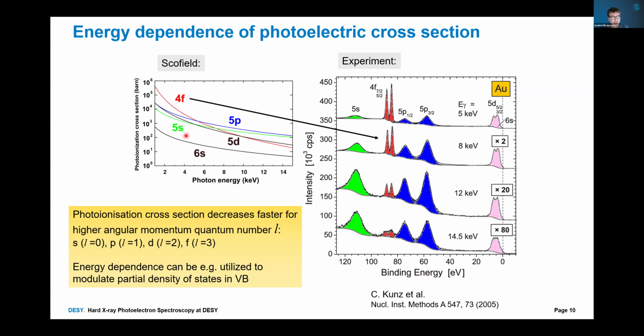and P lines. But this can be used to our benefit, because we can utilize it to modulate the partial density of states in the valence band if we are interested in the subshell contribution to the intensity of the valence density of states. We can vary the excitation energy. So you see here that at low excitation energy, the intensity of F levels is the highest, and then with increasing excitation energy, the relative intensity of F states goes down, and the relative intensity of S, P, and D states dominates in the spectrum.